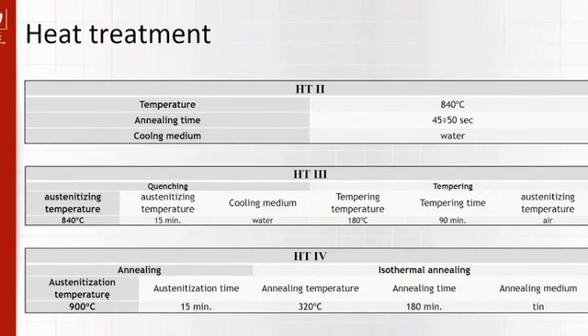The third heat treatment is quenching and tempering, though low temperature tempering, which still makes the internal stresses a bit released. Nevertheless, the hardness of the material remains similar to the hardened material. And the fourth heat treatment was actually quite experimental. It was conducted in order to receive a pure martensitic structure with tiny grains that we could gain quite hard, nevertheless, a pure martensitic structure with relatively plastic properties.